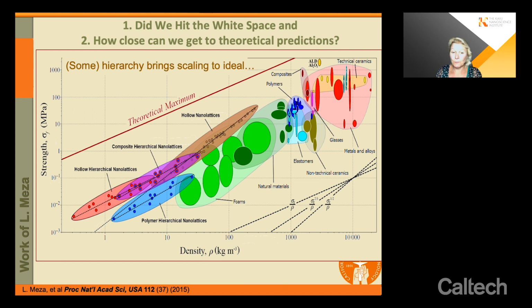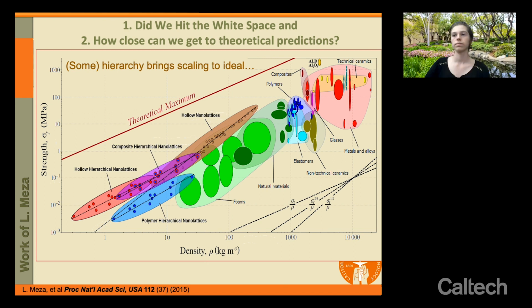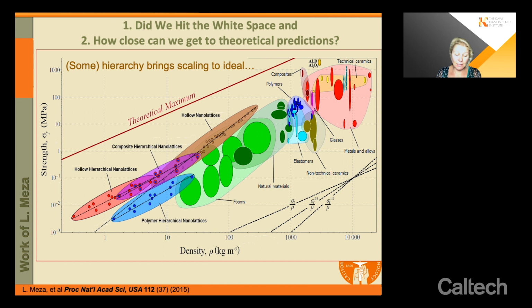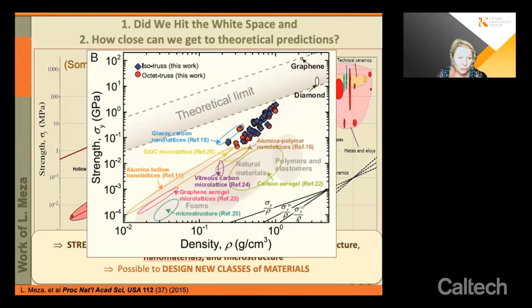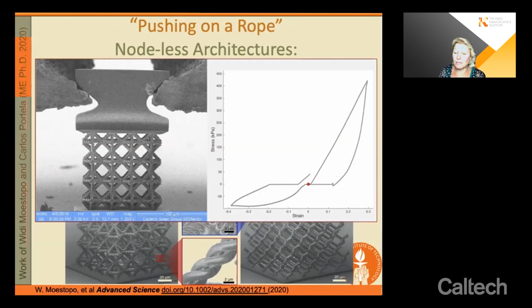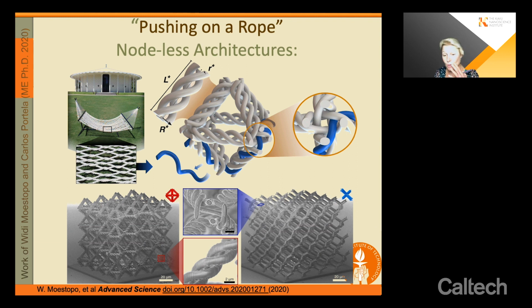Of course, when you create these fractal type architectures, you can see that we've actually fixed the scaling to being linear again, because of their effective load redistribution among the beam members. But that's one of the motivations for why we decided to explore nodeless architectures, which are the woven ones that I showed here. These are the architectures that don't contain any nodes. The idea here is that they would be less susceptible to fatigue because they don't have these strong stress concentrations for initiating damage.